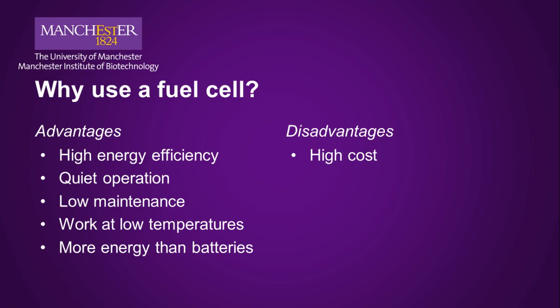The downsides start with the cost, both capital and running costs. The cost of power for hydrogen fuel cells is about 100 times higher than conventionally generated electricity. The precious metal catalysts and the polymer electrolyte membrane are the two biggest capital costs. Hydrogen is difficult to transport and handle, which adds to the running cost. The use of precious metal catalysts like platinum also introduces price volatility and supply issues. The price of platinum since 2000 has ranged from under $15 per gram to over $60 per gram, and a large-scale fuel cell requires about half a gram to one gram of platinum per kilowatt of power.